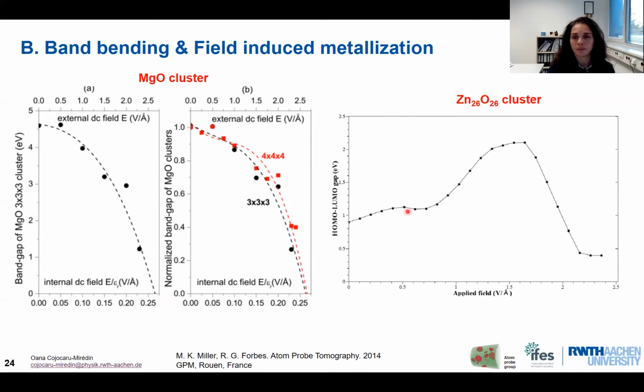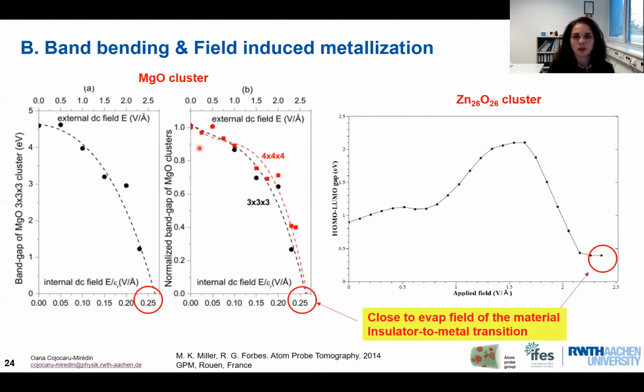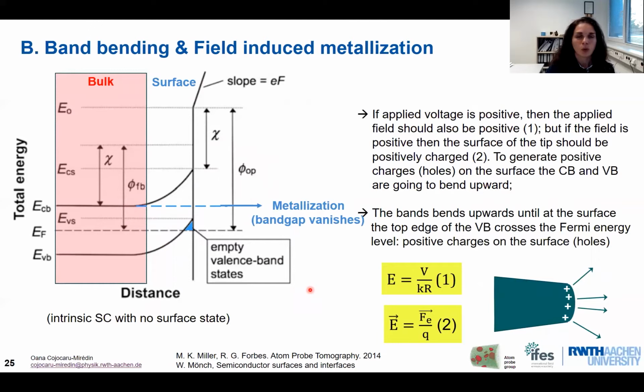So we have a HOMO-LUMO gap which is varying. And then for a certain high electric field, this gap is going to decrease so much that it approaches 0 eV. This is what we typically call band bending, and this is the point where we have an insulator to metal transition, or metallization point. But let's see in more detail what band bending is. Here we have typically a band diagram of a semiconductor material. We know that in the bulk we have the valence band and the conduction band, and we have the Fermi level sitting somewhere in the gap.